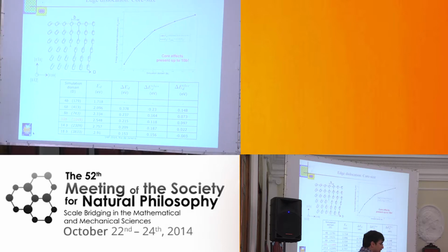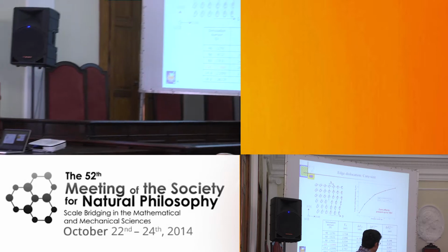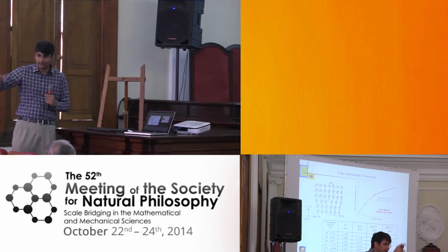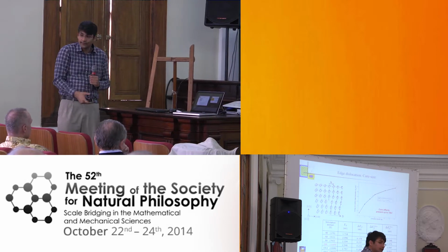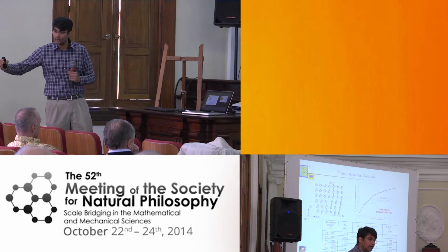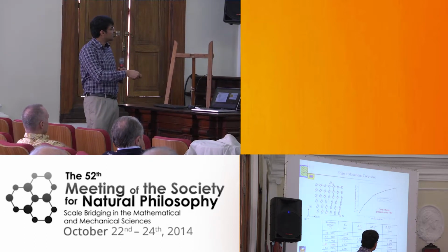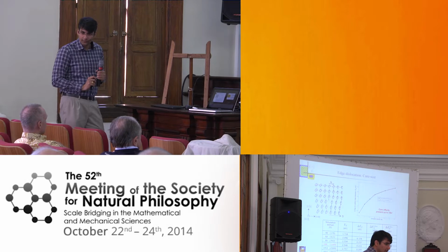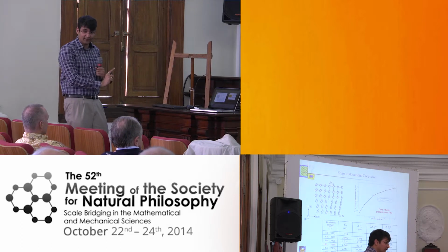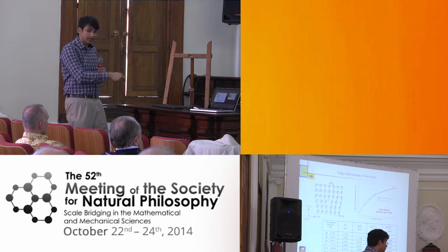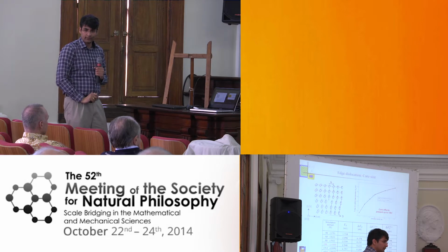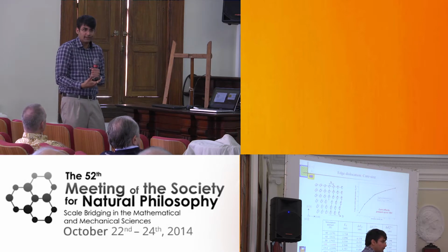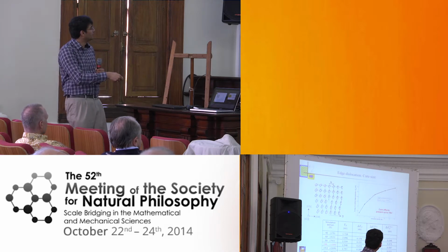And now this change has two contributions. One is the elastic energy in that particular annulus that we have, and the second is the electronic effect, because we're pushing the boundary out. And this can be estimated from the Cauchy-Born hypothesis, again doing orbital-free DFT calculations. So this is computed in full glory, full nonlinear, because orbital-free DFT has full nonlinearity in the calculation itself. And the difference between these two is the electronic effects.